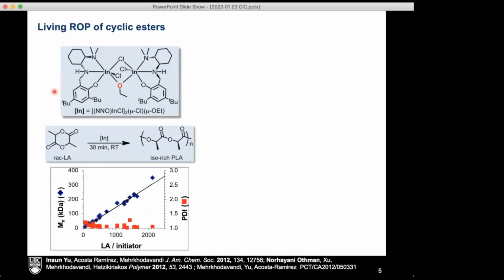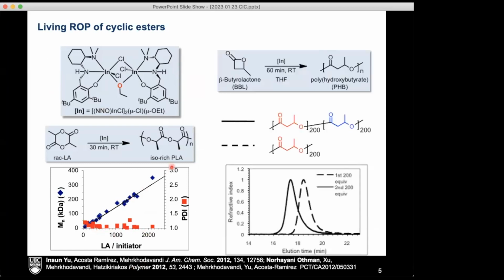So, just a quick highlight of this first system. It's a strange asymmetrically bridged indium complex, a chloroethoxy indium complex, that can polymerize lactide in a very controlled fashion: high molecular weights, low molecular weight distribution. It can handle other monomers like beta-lactone, as well as caprolactone, et cetera, in very controlled living manners. You can add a monomer, watch it polymerize, add another monomer, et cetera, and be able to control the polymer molecular weight.